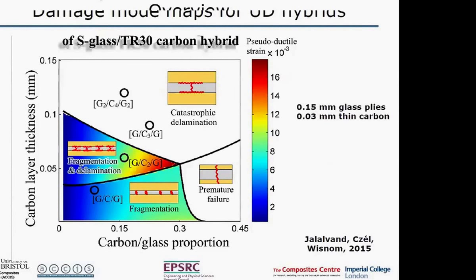So on this particular graph here, we've got a combination of standard thickness glass plies and thin carbon plies. And if we look at different combinations there, we see that if we have 3 or 4 of these thin carbon plies, so 0.03 millimeters, 4 of those is about the standard carbon ply thickness you'd expect from standard pre-preg, 0.12 millimeters. So if you have that, it's too thick, you get delamination. But if you have 2, or only 1 of those thin plies, then you're in this region where you can get this fragmentation mechanism taking place. And if you don't have too much of the carbon on this side of it, then you get the pseudo-ductile response. And in the region here, we can get up to almost 2% for this particular combination of materials.